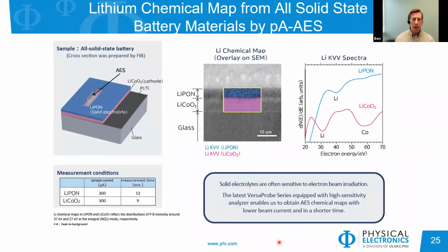Looking now toward more solid state batteries, we have used Auger analysis to characterize the interface between a LiPON layer and a lithium cobalt oxide. With Auger, again, you have a peak for lithium that is at relatively low kinetic energy, as shown here. But we can actually identify slightly different positions of the lithium from the LiPON and the lithium cobalt oxide. One thing, when you're working with these types of systems with an electron beam, you can cause damage to the sample pretty fast. So what we have done here is use quite low sample current and relatively short measuring times to try to preserve the status of these materials.